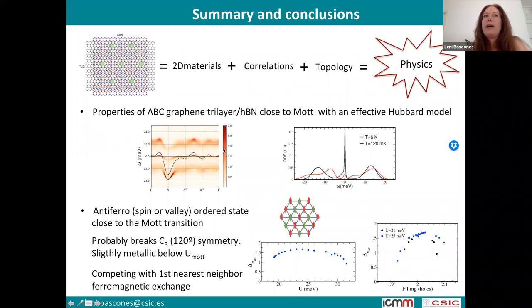And then, with respect to our specific work, we have studied the properties of ABC graphene on boron nitride, aligned with boron nitride, with an effective Hubbard model. And we have seen that we expect to have a strongly modified normal state and dominant temperature dependence. And we have found a state which is antiferromagnetic, and that most probably breaks rotational symmetry, which is maybe slightly metallic. It will compete with other terms that we could have thought we could throw away, and so it's not clear that they can be thrown away. Okay, so thank you.